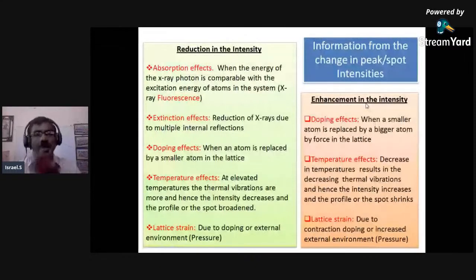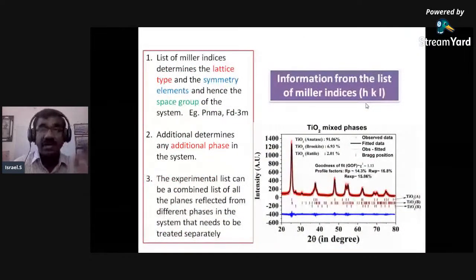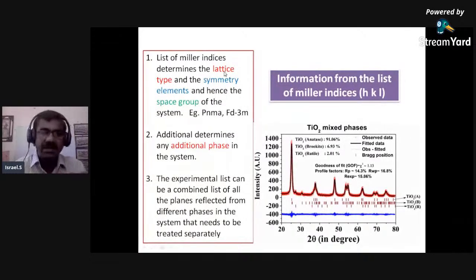Now another information that you get out of the Miller indices. Just looking at the Miller indices, of course, the crystal property, the lattice type you can understand. The 14 Bravais lattices are there, and the space group can be identified. Symmetry elements present in the system can be identified. Apart from that, you can predict the additional phase in the system. Suppose you are growing a crystal of titanium oxide, then this titanium oxide may grow with some mixed phases due to improper growing conditions. If I say an anatase phase of 91% is there, and other phases present in the system, you can understand the presence of these phases, and not only that, the quantifying of this.